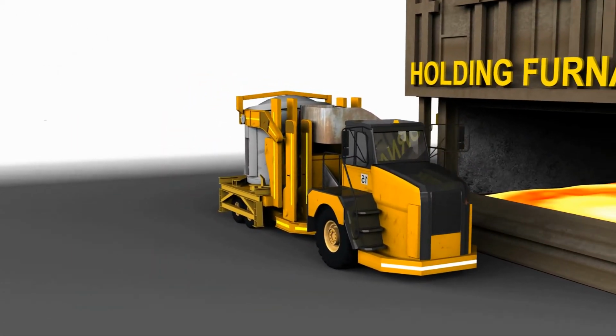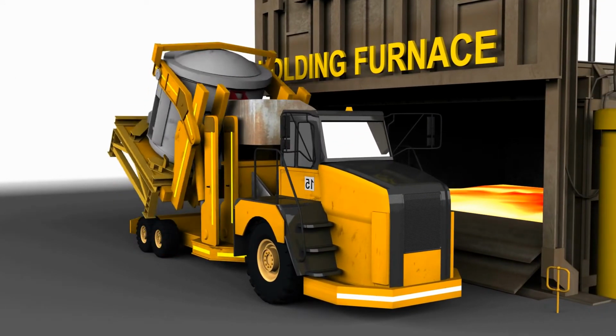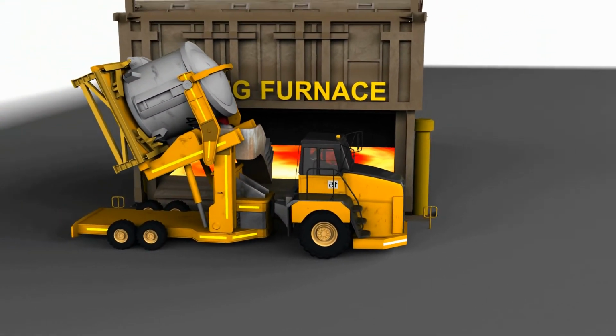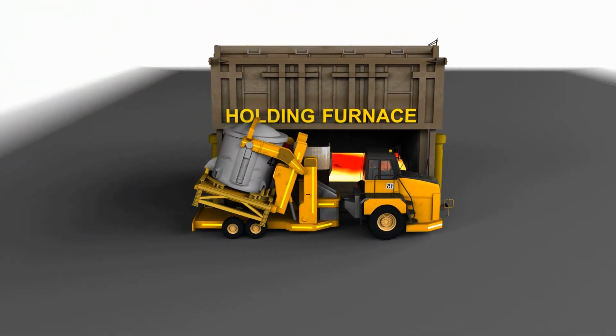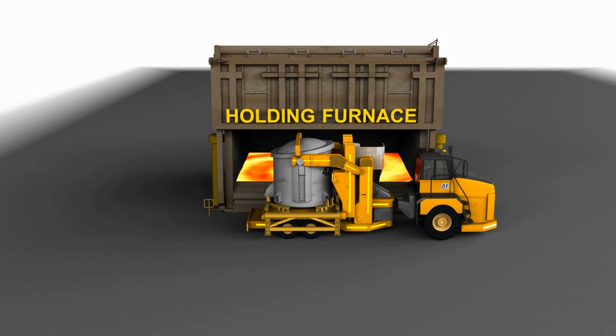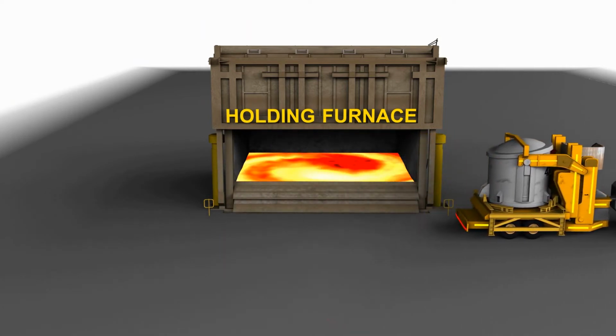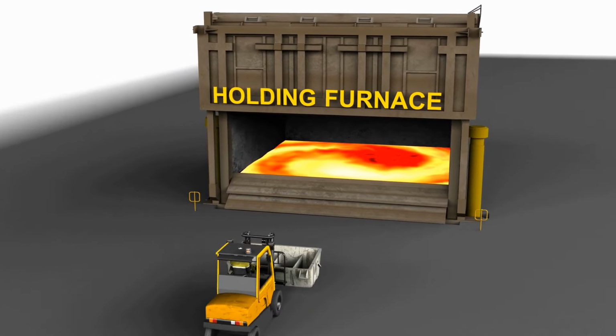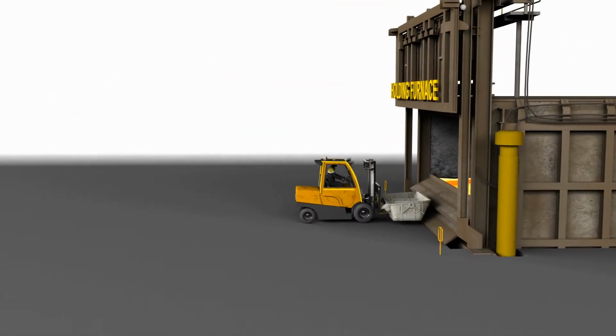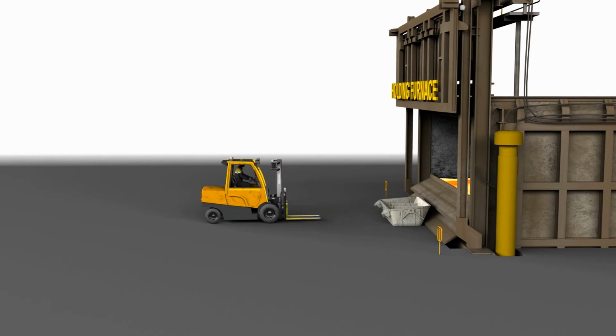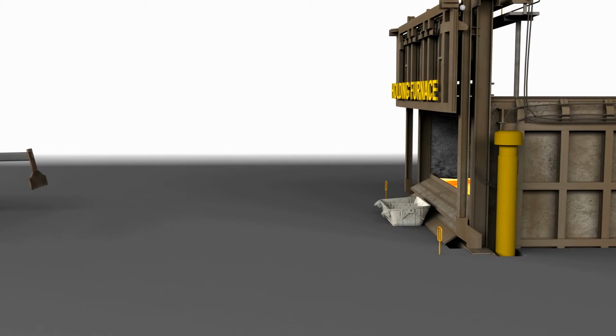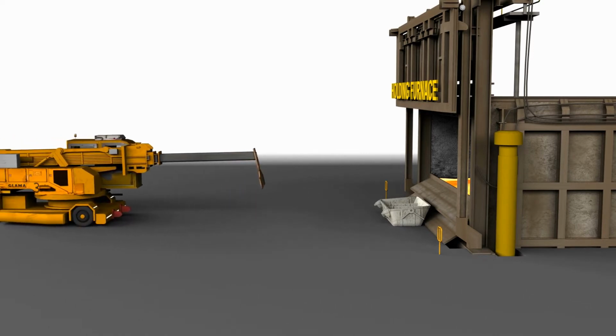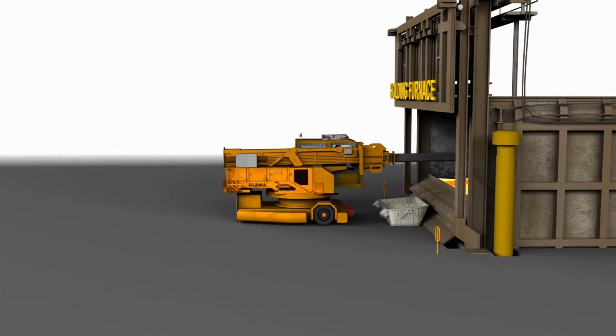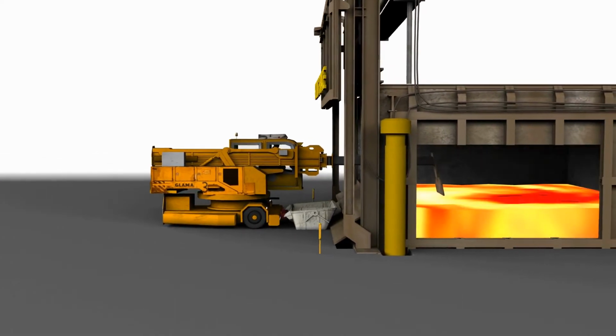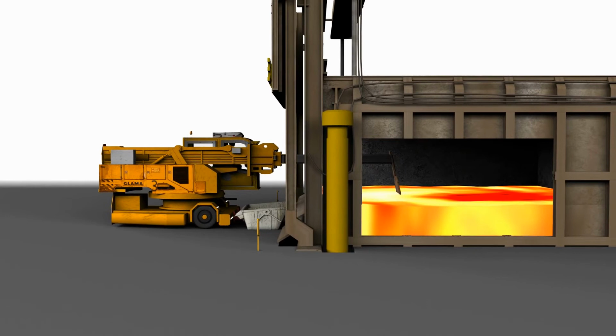The door of the aluminium holding furnace opens. The ladle is tilted so that the liquid aluminium flows into the furnace. The empty ladles are then returned to the weighbridge, where they are collected by the LTVs and taken back to the pot lines. Aluminium in the holding furnace is kept molten by gas burners, which heat the inside of the furnace. Each furnace has a capacity of 60 tons. The vehicle here is called a furnace tending vehicle and has a skimming tool for removing oxidized aluminium, known as dross, from the surface of the metal.